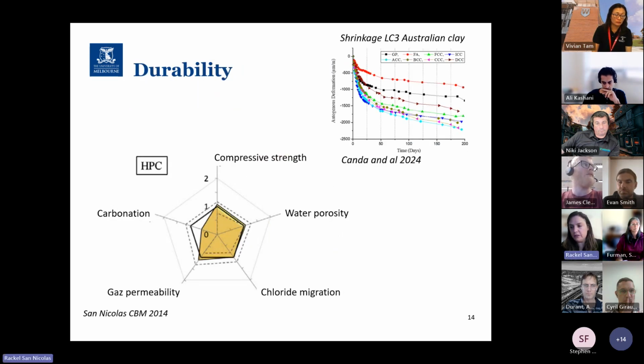I just touched here on the durability, and if you want to have a conversation with me on durability of this kind of system, I can have it. I just put two different representations here. One is about the shrinkage. Some of the systems with Australian calcined clay and shrinkage, there was a beautiful study from UTS showing that, depending on the type of clay you are using, you can have slightly more or a little bit more shrinkage, depending on where you are at and at what time you are assessing the deformation of your concrete. So that's something that we need to keep an eye on, definitely.